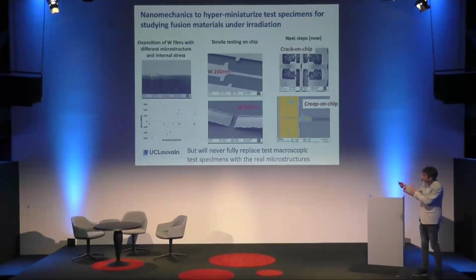This has been controlled, optimized now for tungsten. We were doing this on other materials than tungsten, now adapted this to tungsten. And the ongoing research, as you can see on the slide, involves looking at the propagation of cracks, the toughness of tungsten using these films.